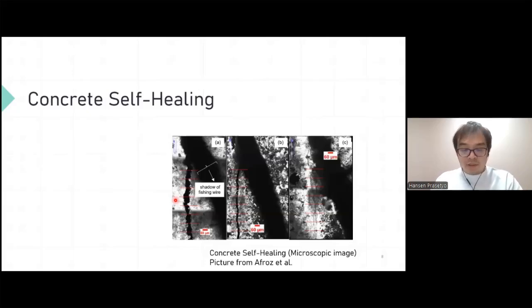And this research, my research, is based on concrete self-healing. This is a well-documented phenomenon that happens when cracks happen in concrete, and then calcium hydroxide reacts with air and water to create calcium carbonate crystals. And these crystals can seal the pores.